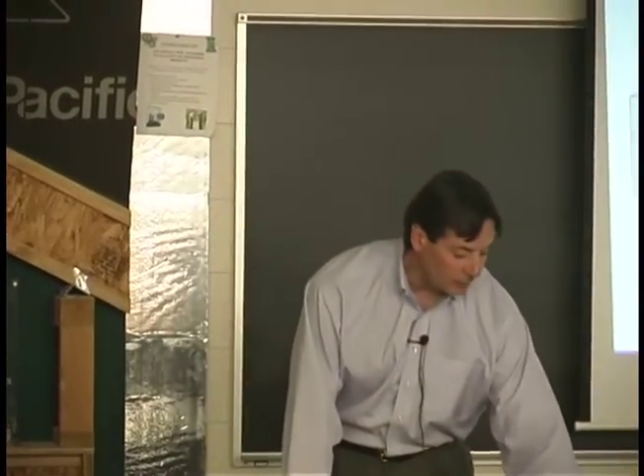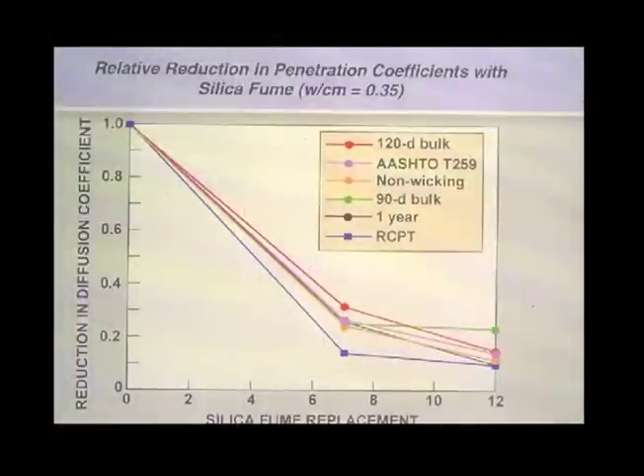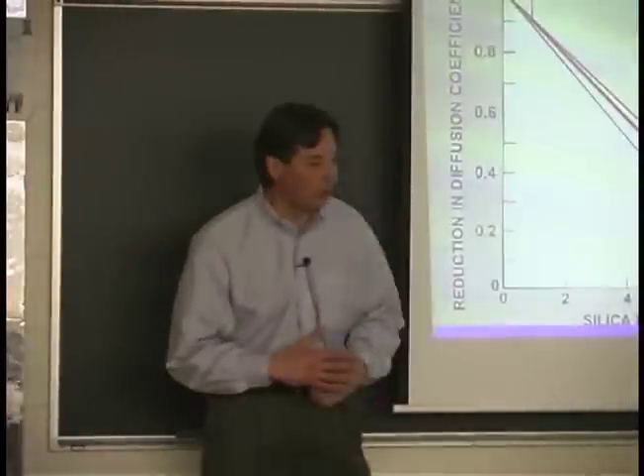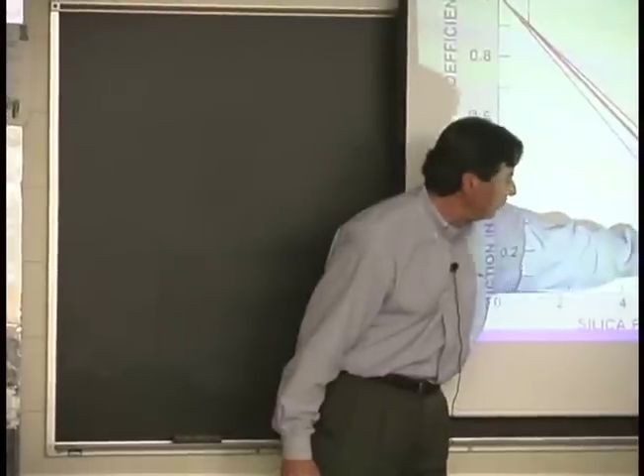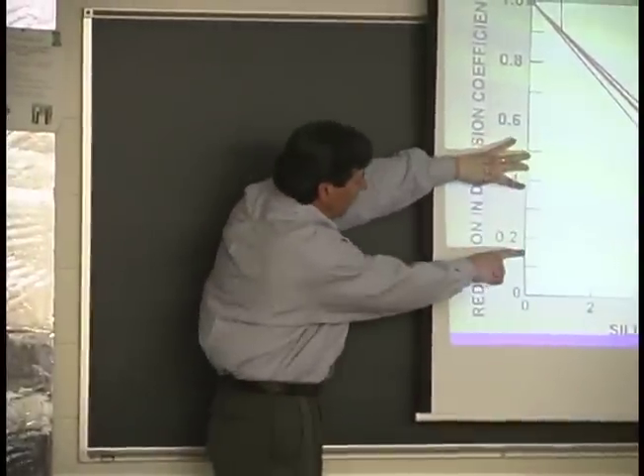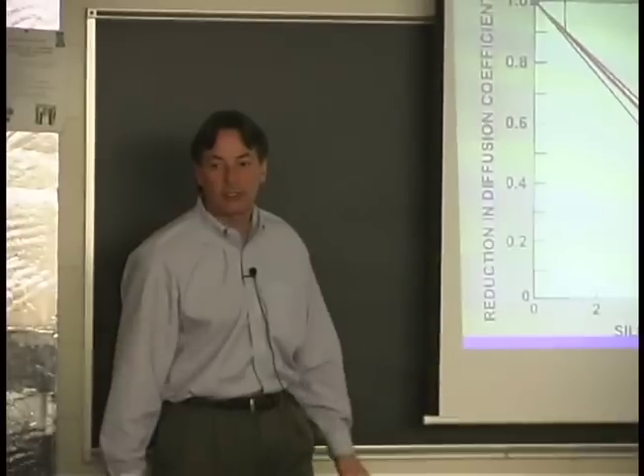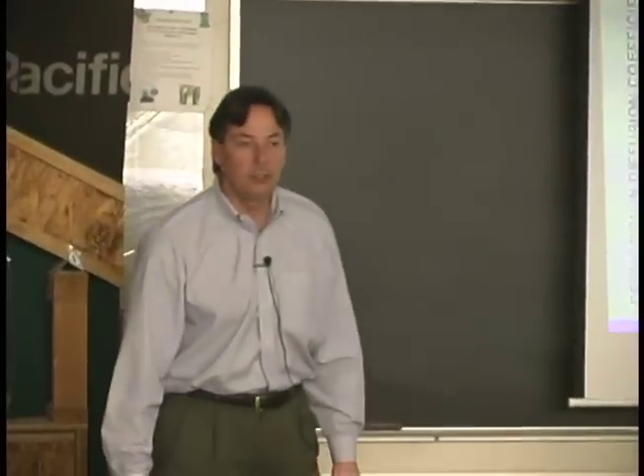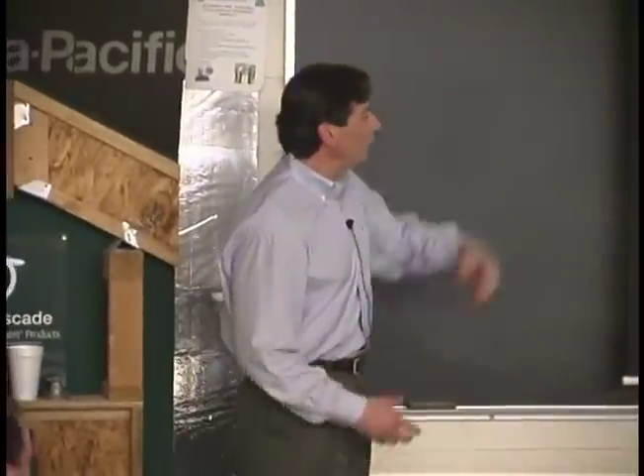So that was always the trend: if you wanted low permeable concrete, you made low water-cement ratio concrete. And what the next slide shows is that's not necessarily the case. You do get a lower permeable concrete at 0.35, which is pretty low, but by replacing the cement with even 7% silica fume, you can get somewhere around 60 to 80% reduction in permeability, even at a real low water-cement ratio concrete.